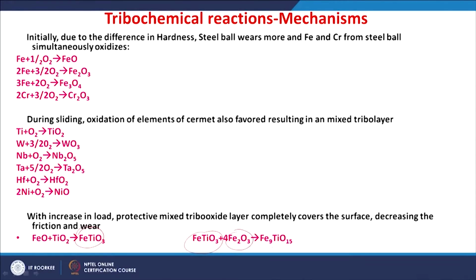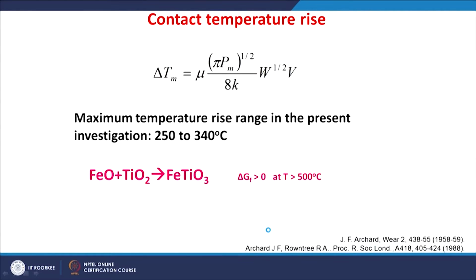So, we have seen the reduced friction and the wear, and our XRD analysis also indicates the formation of an iron titanate. Iron titanate is generally formed by the reaction of the iron oxide with the titanium oxide, or iron titanate further oxidizes with iron and then forms another form of iron titanate. So, we have seen the iron titanates formed from the debris analysis. So, let us understand this tribochemistry involved at higher temperatures with respect to the friction induced